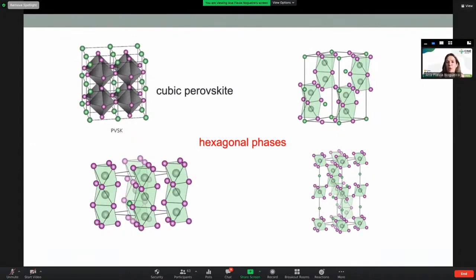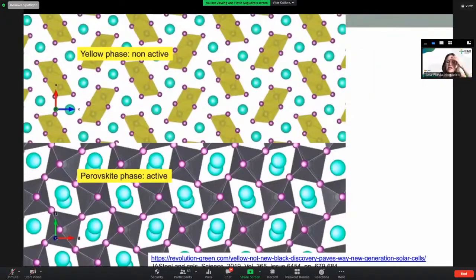So one question was, and I think I didn't mention that, why I don't want this yellow phase. If you look here at the octahedra, we have lead surrounded by six anions. You see here that in the case of the yellow phase, these octahedra are not linked together. Okay, so the transport here is really bad. For the cubic phase, you see that all the octahedra are linked to each other. So this is really what makes the transport very fast in these materials, okay?